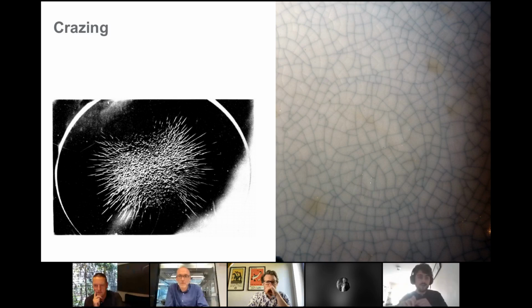One of the first things to note is this phenomenon of crazing. Crazing is an amalgamation of cracking and glazing. It's a word borrowed from the ceramics industry, which you see on the right here, and essentially it's micro cracks that you get on the glazing of ceramics. On the left, you'll see a sample of acrylic, and you see these micro cracks. It manifests itself as a white cloudiness. You might have seen it in plastic: if you try to bend it, it goes a little bit foggy, and that's crazing.